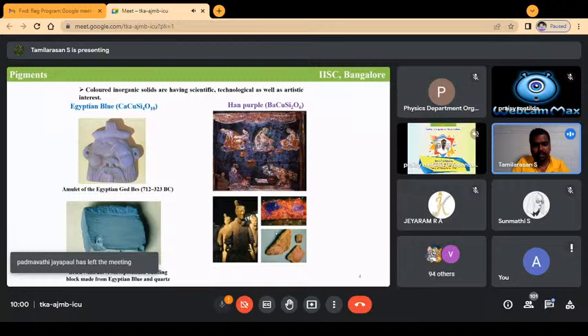But what makes the difference in the color? One is blue, the other one is purple. Though related, it's a difference in band gap. What makes it? If you look at the structure very carefully, in Egyptian blue, copper is square planar coordinated, and it gives rise to blue color. But in Han purple, copper is again square planar, but these square planes are very closely placed, in the sense it makes a metal-metal bond that changes the band gap, giving a different color. So a little change in the coordination environment changes the color, which means it changes the band gap, semiconducting properties, catalytic properties. That gives a lead to investigate more materials.